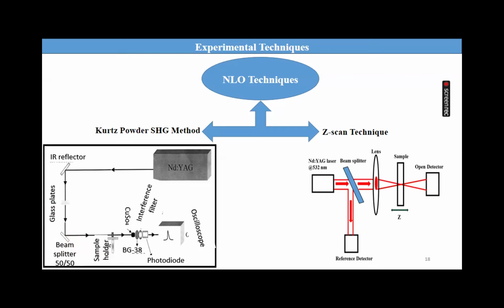The amount of light that the sample emitted was measured using a photodiode detector and oscilloscope combination. The emission of green radiation at 532 nanometer and the optical signals were collected by a photomultiplier tube. In a comparable capillary tube sealed at one end, microcrystalline powder of urea or KDP was taken for comparison. We compared the sample's second harmonic output intensity to that of either KDP or urea.